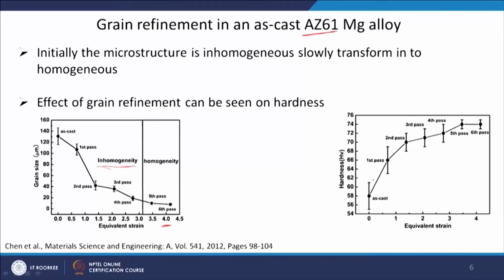By third pass, because you have done the whole cycle, homogeneity will start coming in the material, which was not there in the rolling process or the ARB process, because your continuous deformation directions remain the same. There you will see elongated grains and so on, but in ECAP, if you are using BC route or multi-axial forging, you will start seeing an equiaxed microstructure.